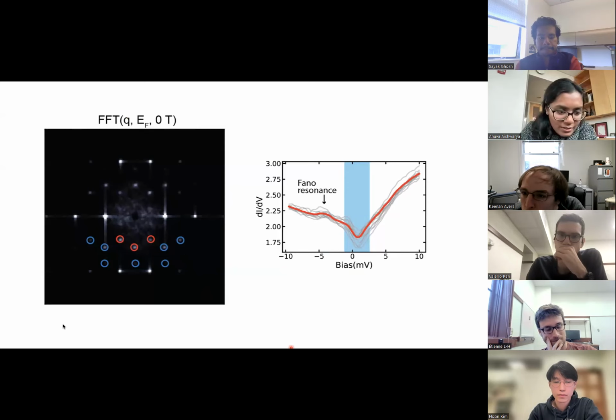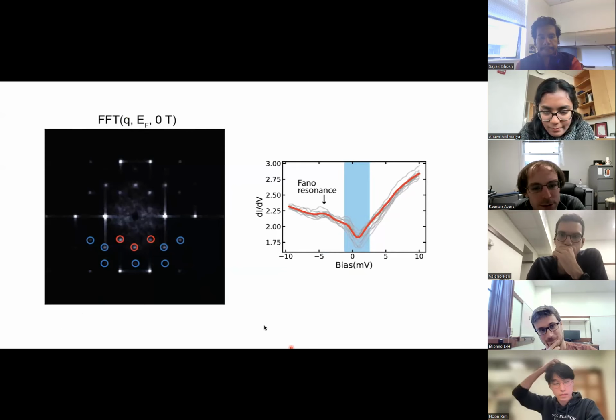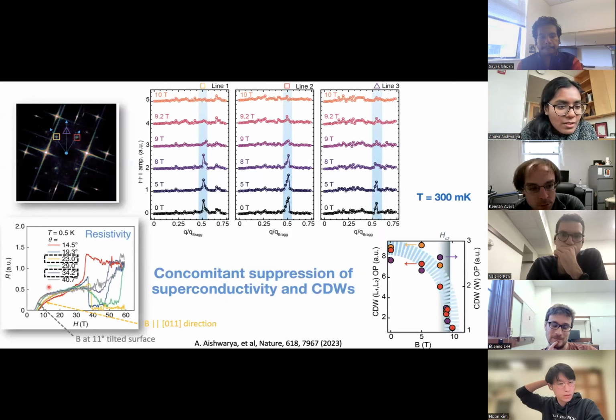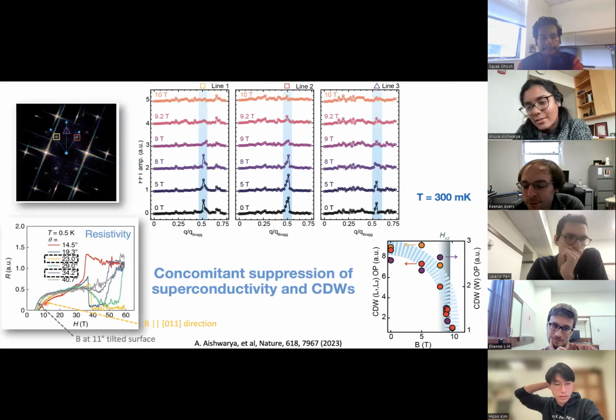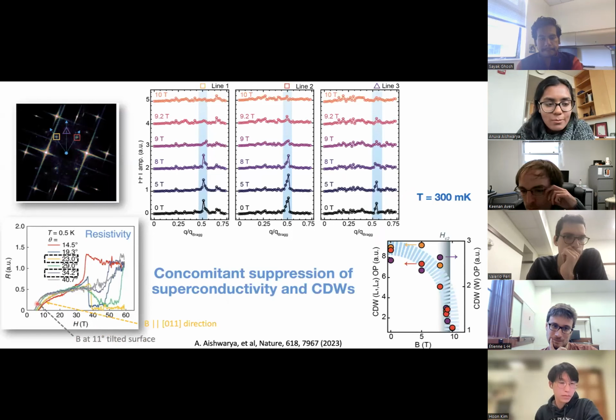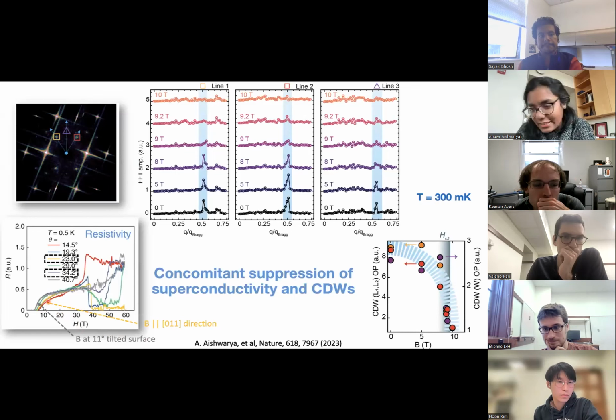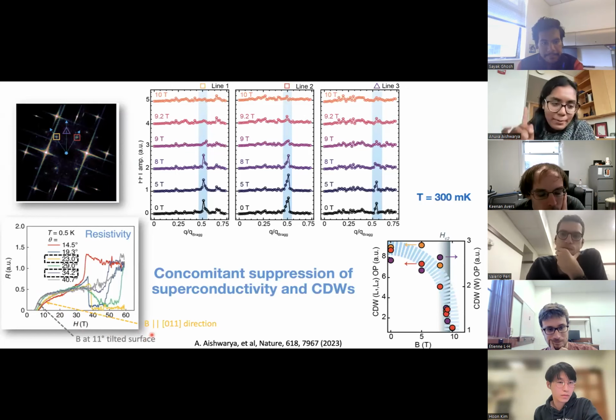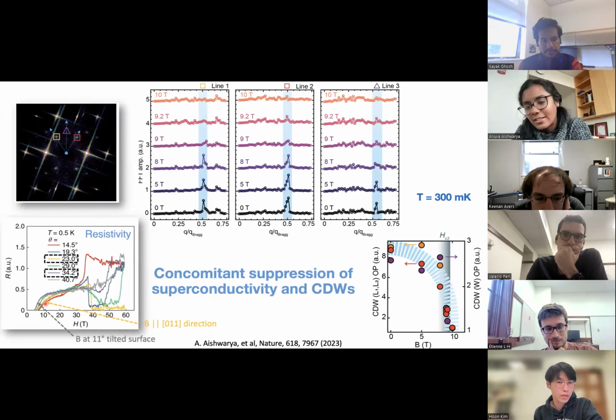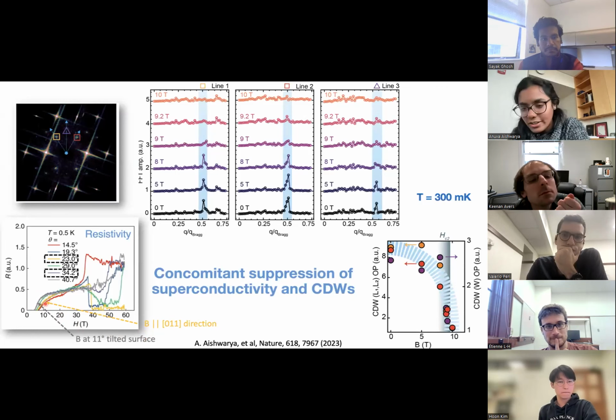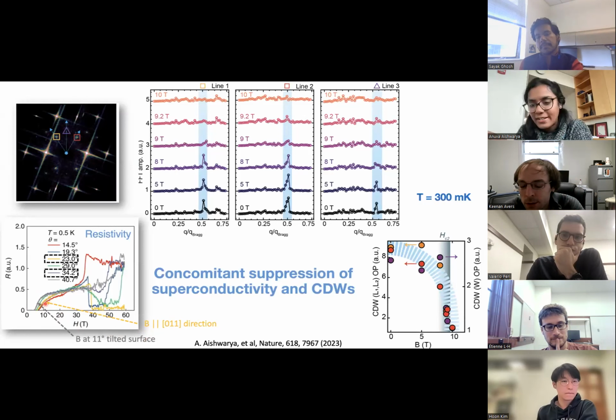Because if you look at transport here, I'll just go back to my slide. Here. If you look at these two curves, compare the yellow and the gray, you can see that the HC2 is different for these two directions. One of them is slightly smaller than the other. So when you go to the direction which is slightly smaller, you can actually suppress the entire CDW. So if we had access to, let's say, 15 Tesla in STM, and we had a perfectly flat sample and applied a magnetic field, then probably we can also kill the CDW in that direction. So the suppression of the CDW is not dependent on the triplet character, but the dependence on direction is. I hope I have made myself clear.